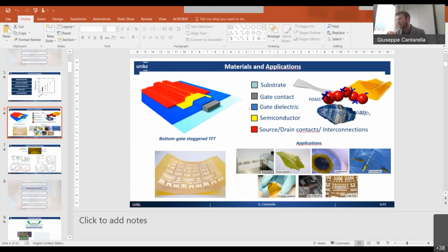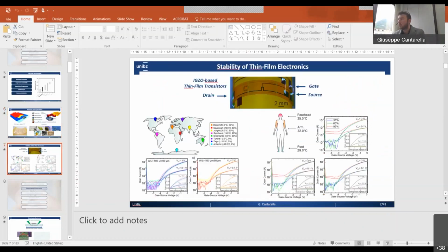Yes, absolutely. The idea is that every time, this is probably not perfectly visible from this image here, but maybe it is here. What we do is pattern everything with UV photolithography. Each layer that I presented to you, from the gate metal up to the last metal, or the passivation, depending on the specific sample, is patterned with UV photolithography and then etched by wet etching. So we don't use dry etching. With this approach, we usually achieve a resolution, so the distance between our source and drain, of 3 microns.